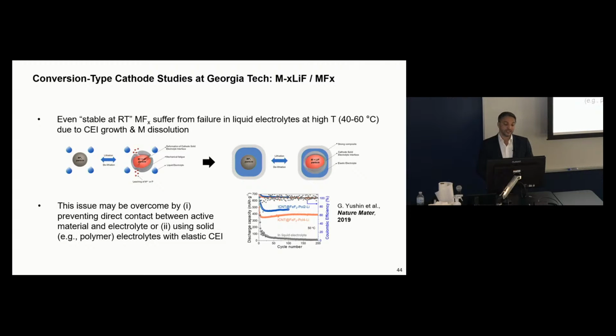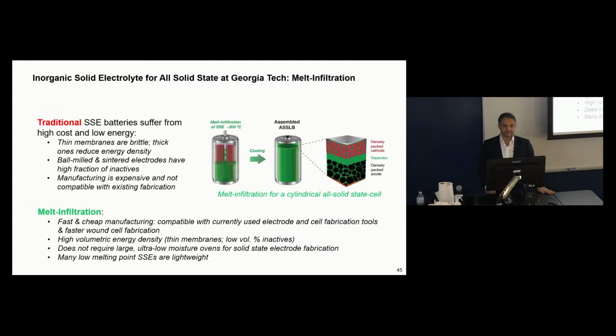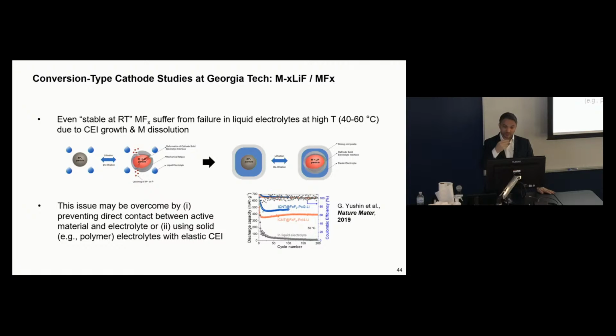And so there are two challenges, two ways to overcome it. Either you figure out how to make perfect protective coating, so these materials didn't have any protective coatings, or you can use electrolytes that do not have these significant reactions with active material, right? That do not dissolve these materials. And so then, in this case, we use polymer electrolytes, and you could achieve good stability. Another advantage might be a synergy between polymer electrolytes, or many solid electrolytes, and conversion-type cathode is that many solid electrolytes that operate well at low electrochemical potentials, they have stability issues at high voltages.